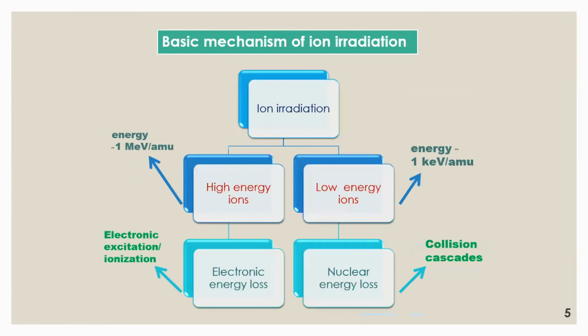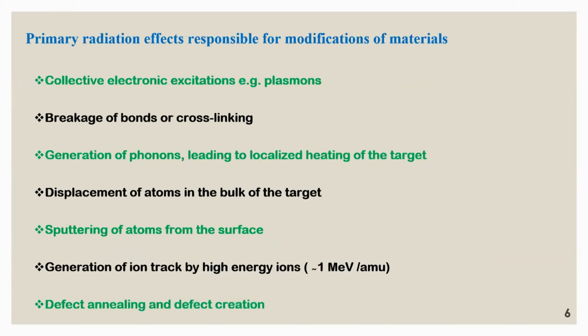This is the basic mechanism of ion irradiation. Ion irradiation is divided into two parts, that is, high energy ions and low energy ions. High energy ions have energy approximately equal to 1 MeV per amu, and low energy ions have energy approximately equal to 1 keV per amu. Electronic energy loss dominates at high energy, which gives electronic excitation and ionization, whereas nuclear energy loss dominates at low energy, which gives collision cascades.